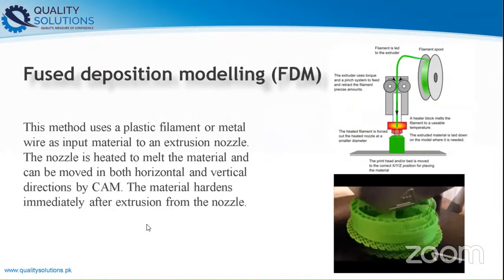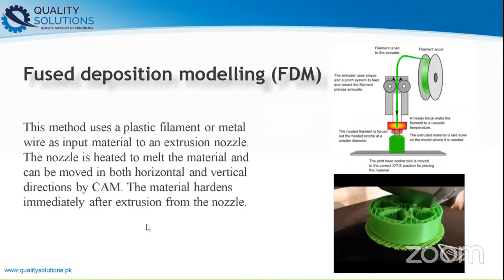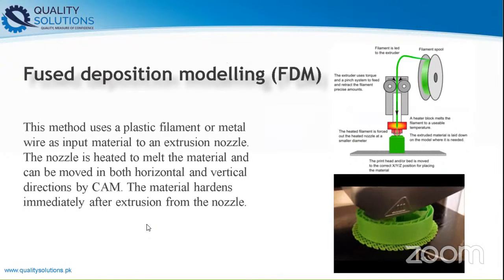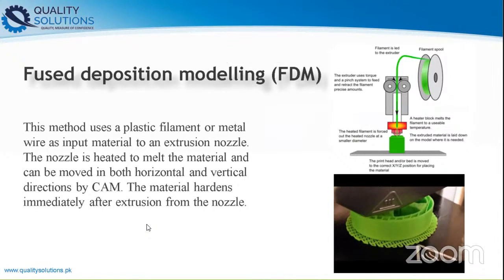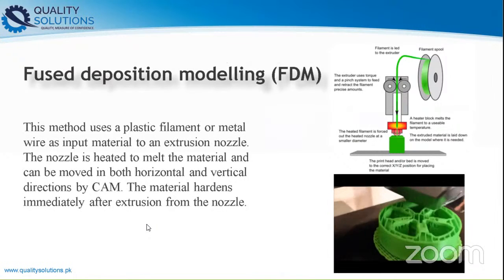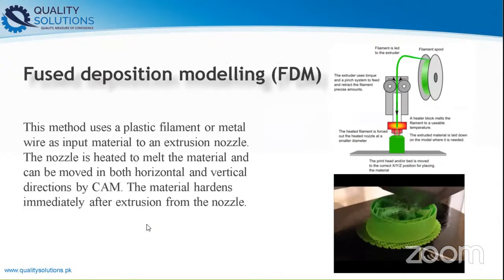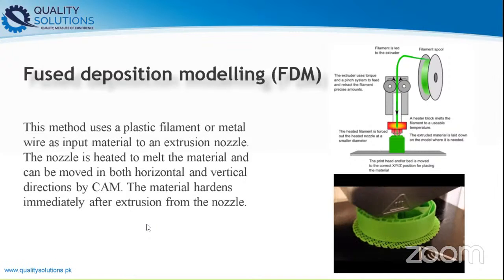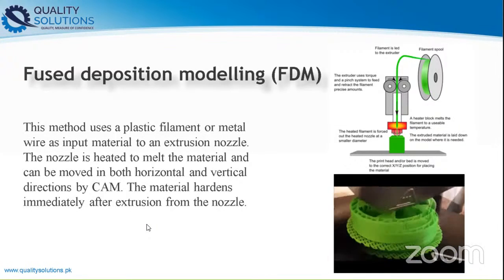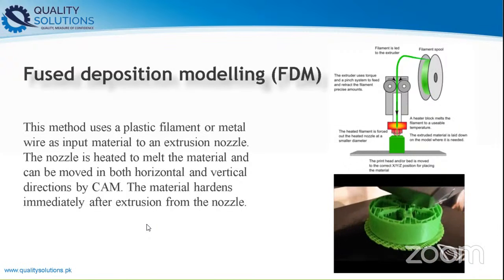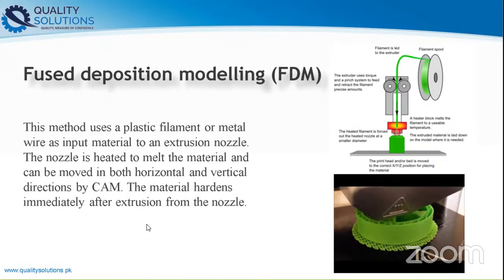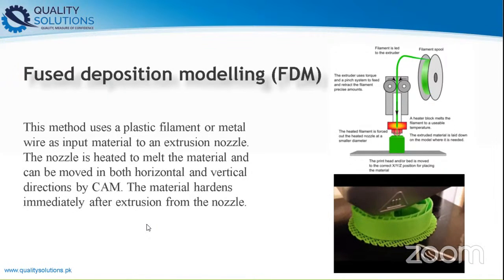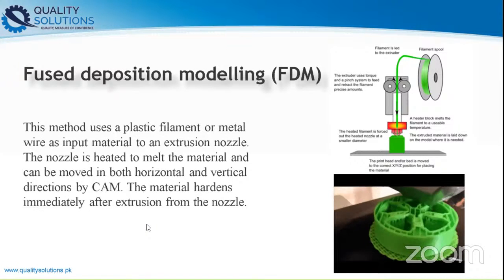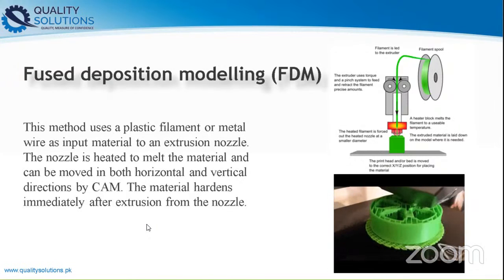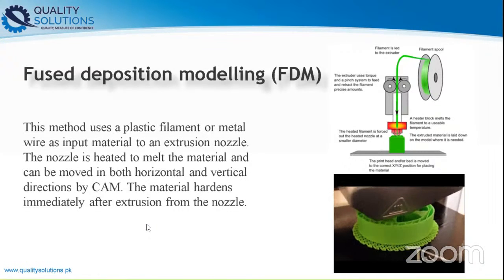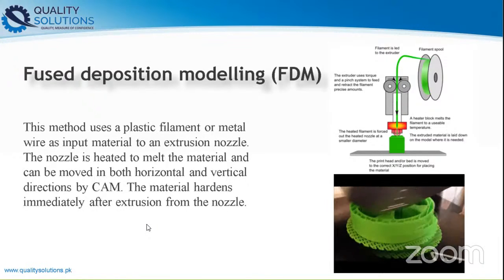FDM, the fused deposition modeling, is best suited for low cost prototyping where form and fit are more important than function. FDM produces parts one layer at a time by extruding a thermoplastic onto a build plate. For large parts, this can lead to big variations in temperature across the build platform. As different areas of the part cool at different rates, internal stress causes the print to deform, leading to warping or shrinkage. Solutions like printing rafts, heated beds, and radii at sharp edges and corners can help to reduce this.